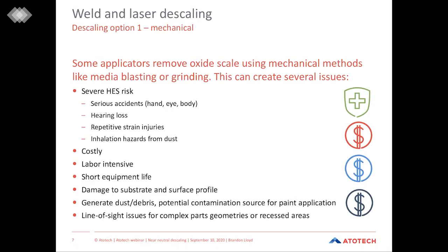These processes are costly. They are very labor intensive, especially the manual applications. Due to the nature of the application and the stress that it puts on the equipment, it often results in a very short equipment life. It does create some damage to the substrate and the surface profile that can result in paint defects or a change in the aspect of the paint coating itself. It does generate dust and debris, which is a potential contamination source for paint applications, which again can result in a lot of defects.